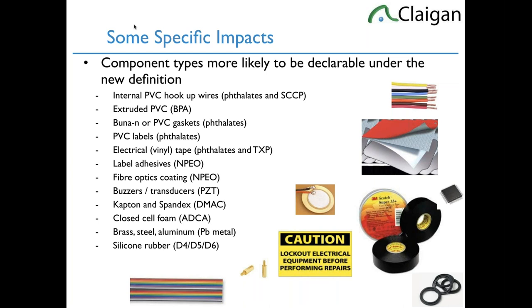Super common, a little white disc inside with a little electrode there. It's almost 100% PZT. Very common declarable, but it's not banned. You just have to declare. As long as you say my buzzer contains PZT, you're compliant, above 1%. Kapton, elastane, spandex, and non-woven fibers are made using a solvent called DMAc, one of the aprotic polar solvents. It's usually residual in those materials, still about 0.1%. So often the Kaptons of the world and spandex and elastanes have residual DMAc.